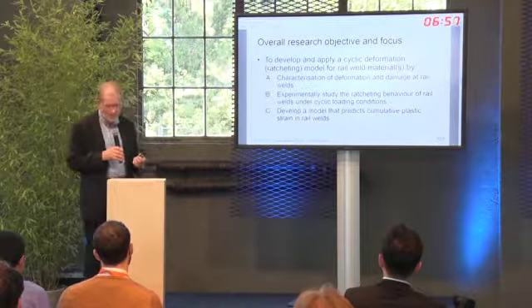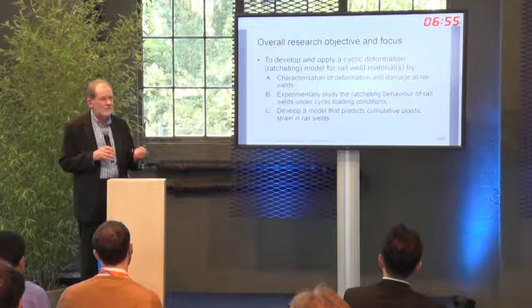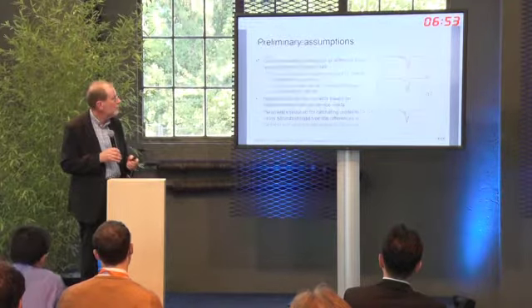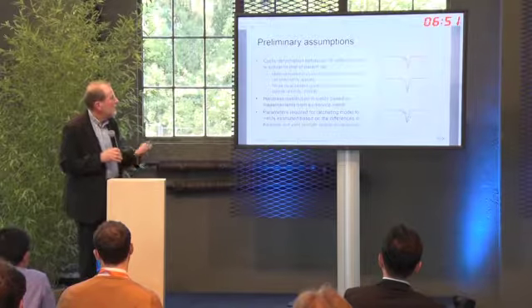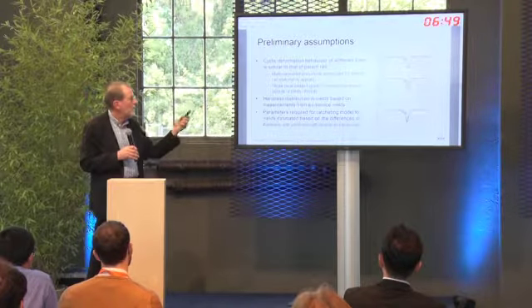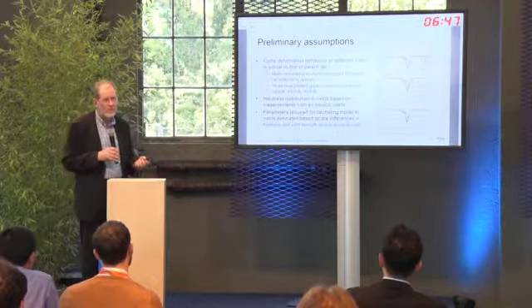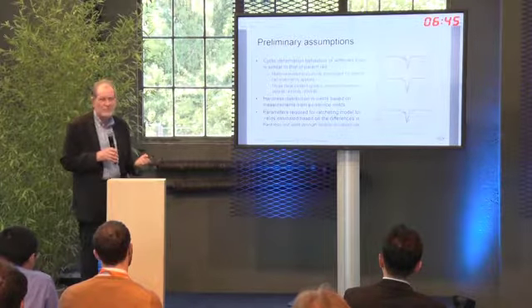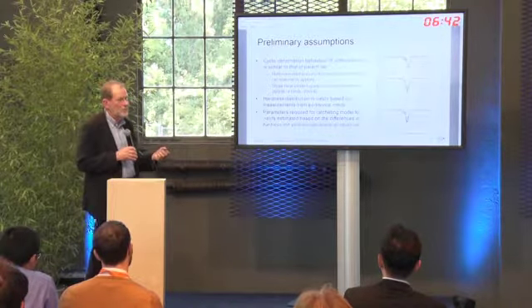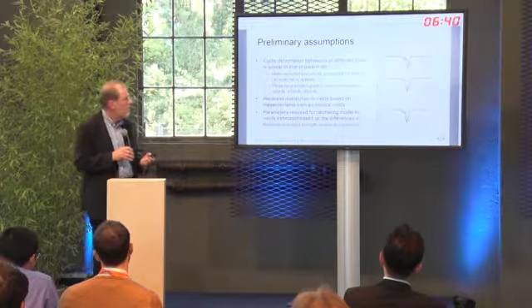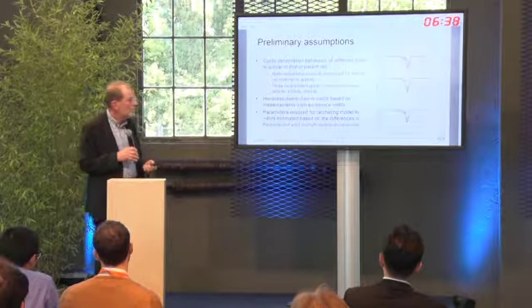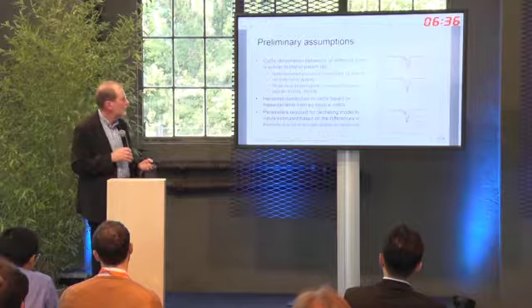It's at very preliminary stages, and I'll just illustrate the approach that we've taken. So the preliminary assumptions were that the material model would be similar to that of the parent rail, which is obviously grossly inadequate, but it was really to set something up so we could look then at the sensitivity to the heat affected width of the softened zone.